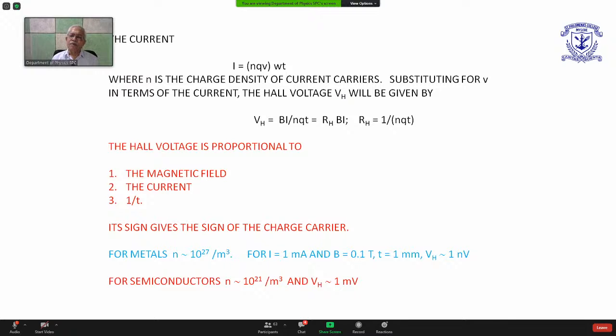And if thickness is about 1 millimeter, it turns out that for metals, the Hall voltage is 1 nanovolt, very small. So unless you have a very sensitive nanovolt meter, you may not be able to measure that. That is why in our BSc or MSc laboratories, we often do Hall effect experiments using a semiconductor, not a metal. For semiconductors, the carrier density is much smaller by a factor of 1,000,000, and therefore the Hall voltage is up by a factor of 10 to the power of 6, and it could be of the order of 1 millivolt. So this gives you an idea of what is the Hall voltage in semiconductors and metals.